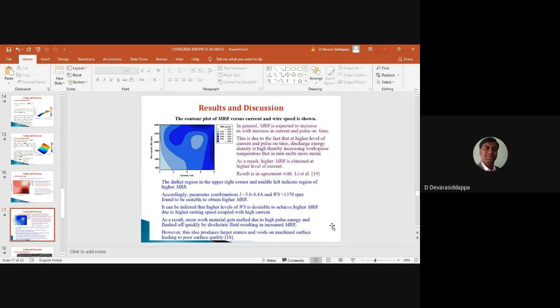As a result, more work material gets melted due to high pulse energy, and it is flushed off quickly by the dielectric fluid, resulting in higher MRR. However, the high pulse energy impinging on the surface will also create craters and voids on the machined surface, leading to poor surface quality. This has to be carefully selected.